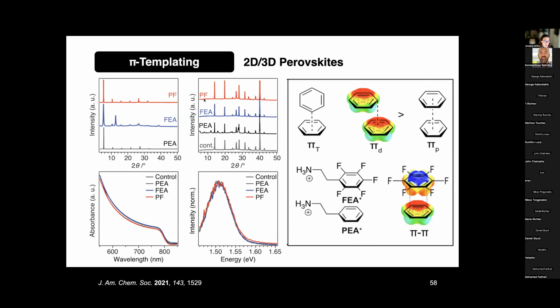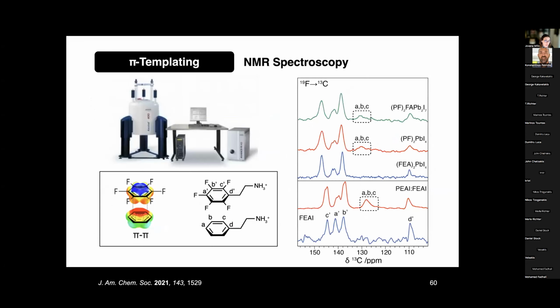And similarly, the three-dimensional perovskite structure is maintained despite the capacity of each of these systems, so the PEA, the non-fluorinated, the perfluorinated FEA, and their one-to-one mixture labeled as PF, to form this well-defined two-dimensional perovskite phase, as illustrated by these typically layered periodic X-ray diffraction patterns. Here, we need to be careful in assessing their properties by solely relying on XRD, as this is primarily the result of the inorganic framework. So to really gain insight into the behavior of the organic components and their supramolecular assemblies in the spacer layer, we had to complement this analysis once more by solid-state NMR spectroscopy.